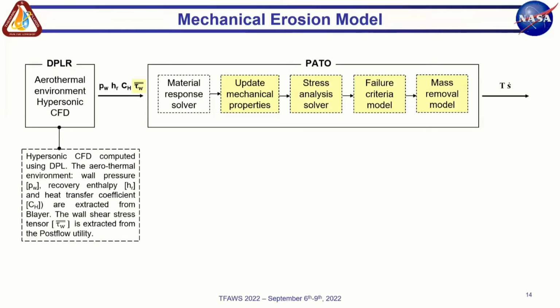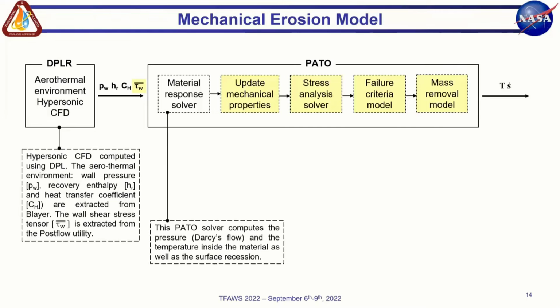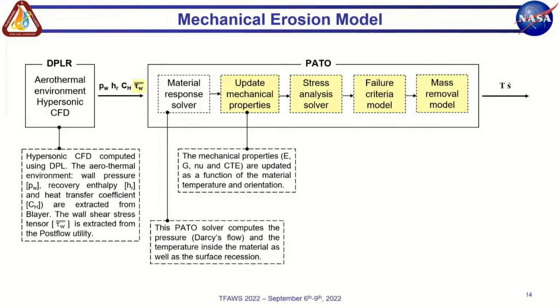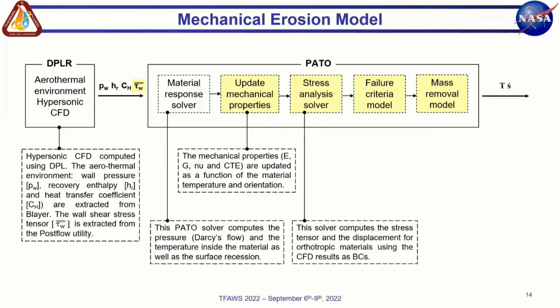Having the results from DPLR, the thermal environment is extracted with B-layer, and the surface and the wall shear stress tensor is obtained from the post-flow utility. Then PATO's material response solver computes the pressure and the temperature field inside the material as well as the surface recession. And the next step is updating the mechanical properties of the material as a function of temperature, accounting for the local orientation of the material itself. And then the stress analysis solver computes the stress field and the displacement using the CFD results as boundary condition.